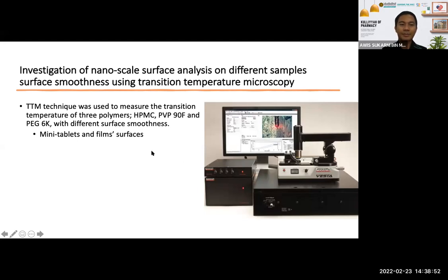In this study, basically, I'm using the TTM to measure the transition temperature of 3 different polymers: HPMC, PVP 90F, and PEG 6K with different surface smoothness. In this case, I chose a mini tablet and the film surface. The mini tablet, because it's basically direct compression, so the surface can be rough compared to the film, which has a very smooth surface.